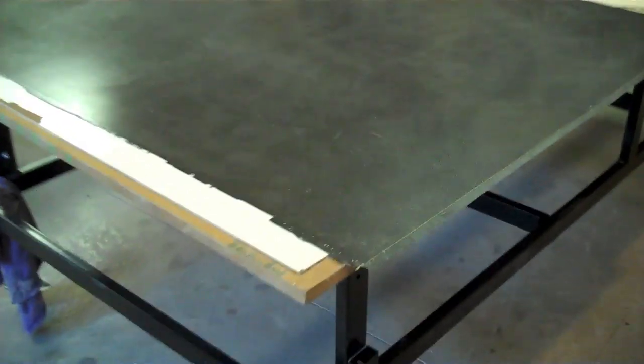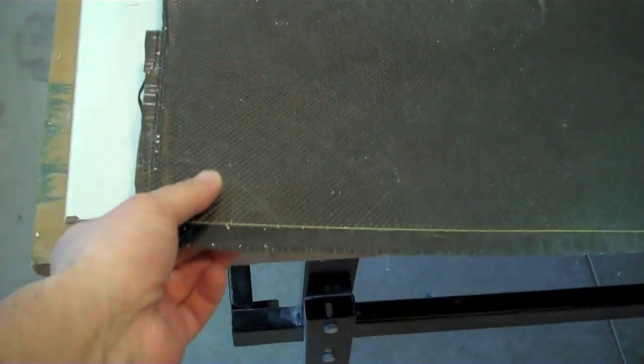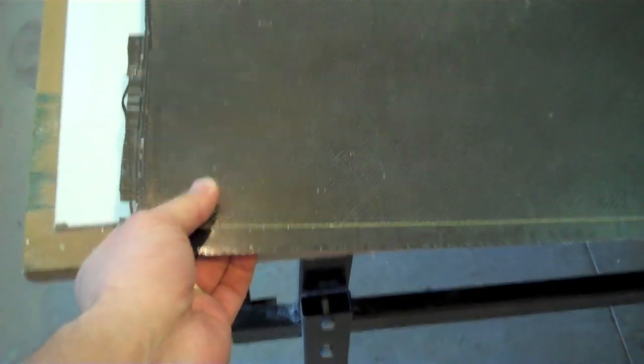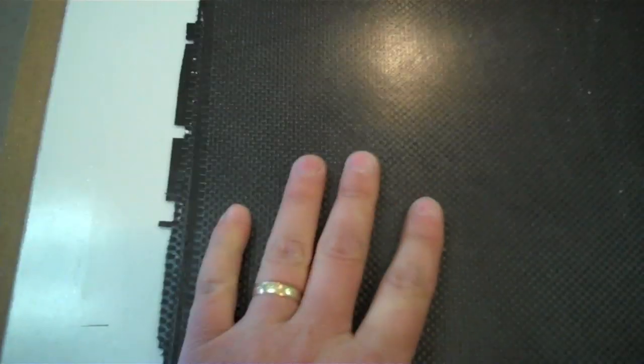Okay, here's the final product of the carbon fiber sheet that we made. We haven't trimmed the edges yet. This is seven layers of carbon. You can see the shiny side is the side that was down on the table. It's about a four foot by four foot sheet. I think it's actually 48 inches by 52 inches. This is what we're going to use for any flat stock that we need. It's real light. You can see on this side the texture of the carbon. That's how you can tell that you've got just enough resin in it and not too much. And we'll trim off these edges because these are actually like razor sharp. This will be our sheet stock for when we need a flat area or for when we make the edges around the windows where we're going to put the windows on.